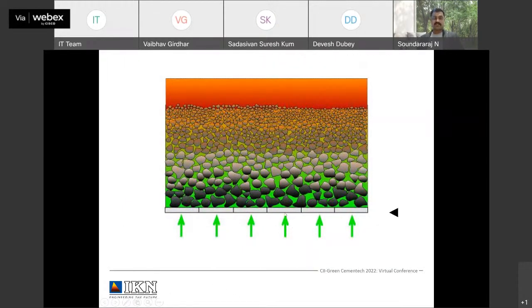And if you see the cross section of the IKN bed, which is made based on the Coanda effect, there will be layers of clinker, fines at the top and coarse at the bottom. This can be achieved with the Coanda effect and partial fluidization. The advantage of such segregation is the uniform heat up of air from bottom to the top when it passes the bed. The fines will have most of the latent heat. When the air enters at 30 degrees and is slowly getting heated up, it reaches 1100 or 1150 or 1200 degrees, whatever is possible, and it leaves the bed to the recuperation.